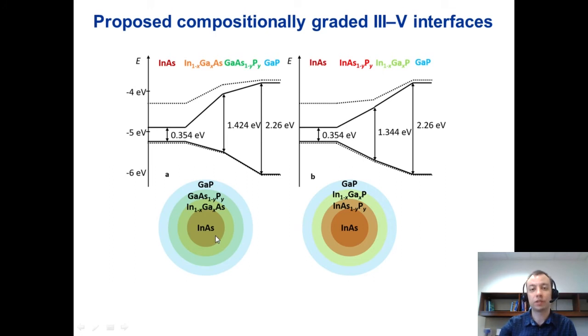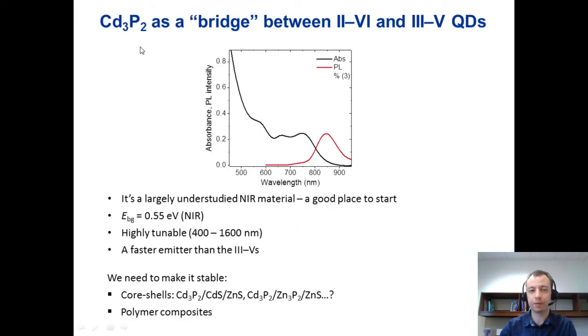So a good place to start would be, in fact, cadmium phosphide quantum dots, which is kind of a bridging system between II-VI and III-V semiconductors. These quantum dots somewhat resemble cadmium selenide, but they are a near-infrared material with a bulk band gap of about half an electron volt. But owing to their high quantum confinement, the photoluminescence is highly tunable over the visible range of the spectrum and the near-infrared range up to 1600 nanometers.